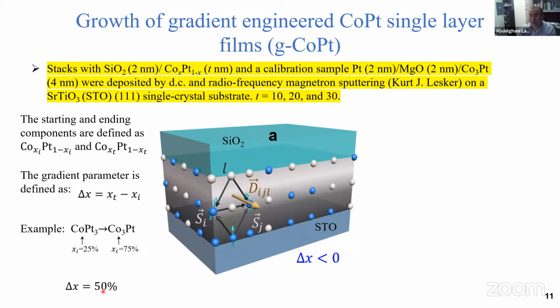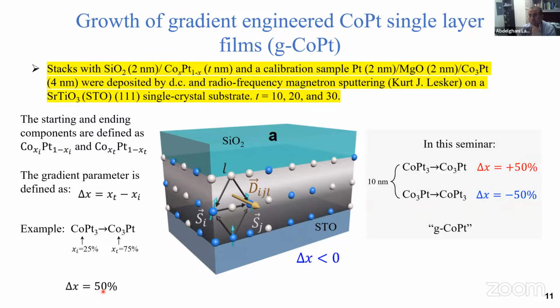So in this talk today in particular, I will only show the results on 10 nanometer thick films, where we have both positive and negative gradients. I mean, whether you go from cobalt platinum 3 to cobalt 3 platinum, or cobalt 3 platinum to cobalt platinum 3. And then we refer to these gradient composition engineered films as GCoPt.